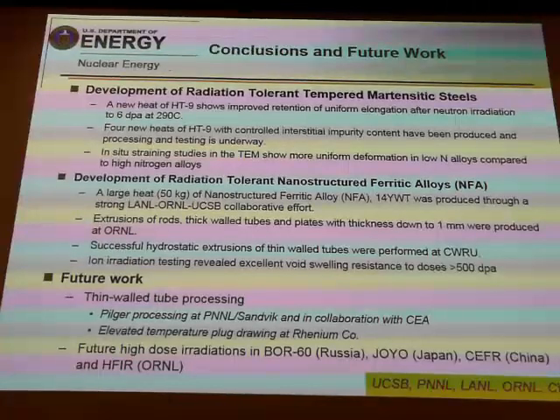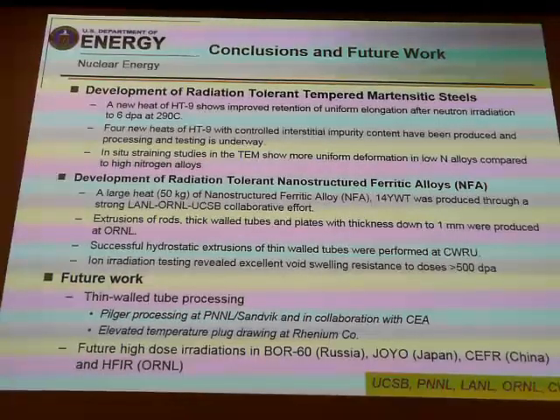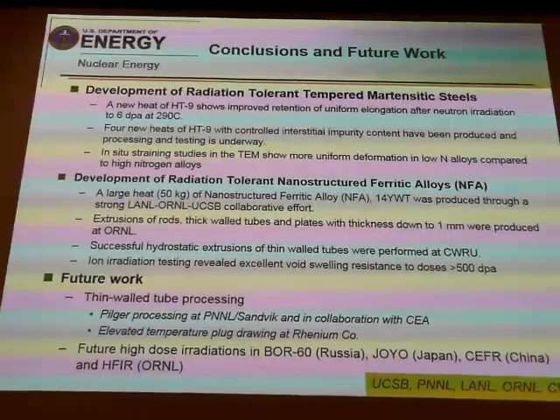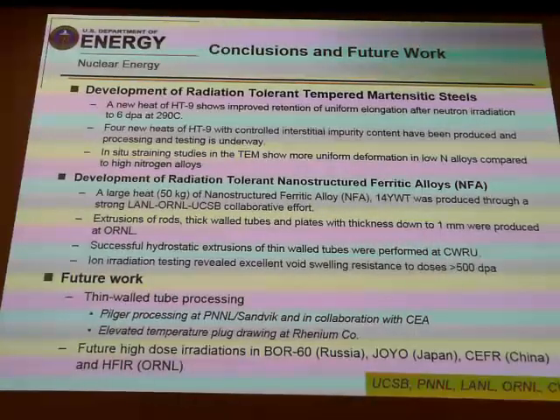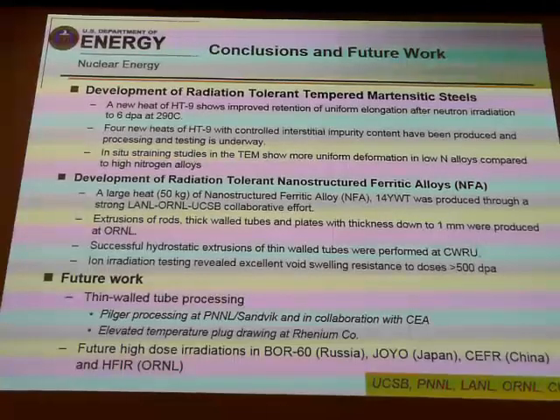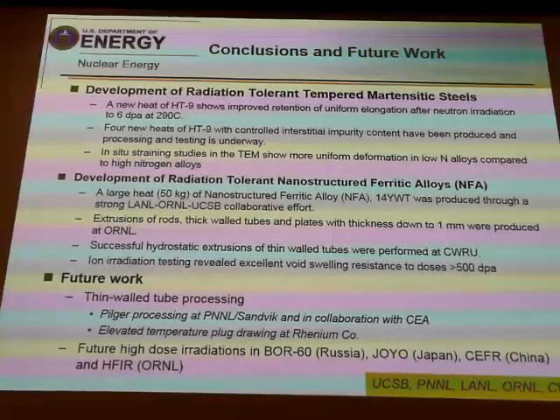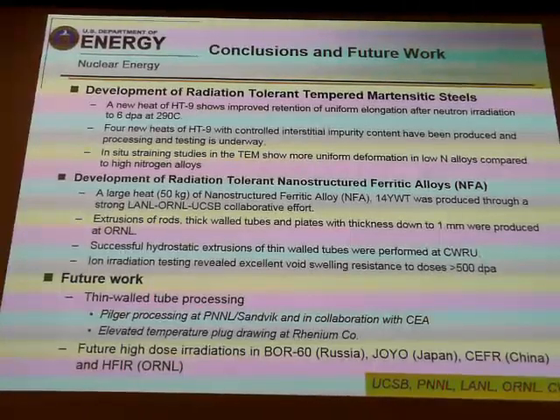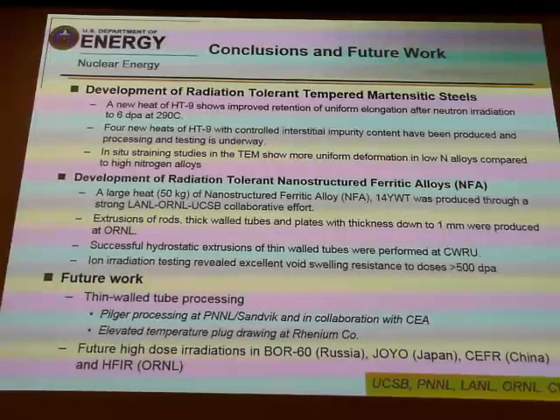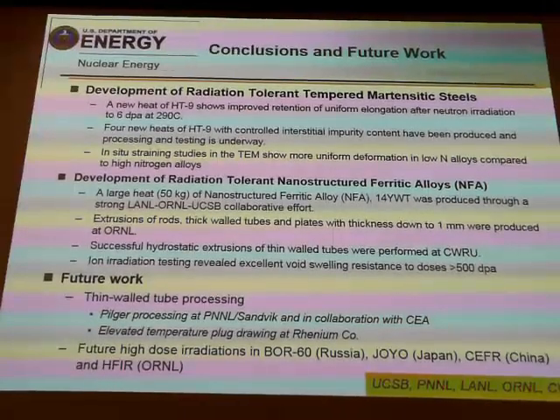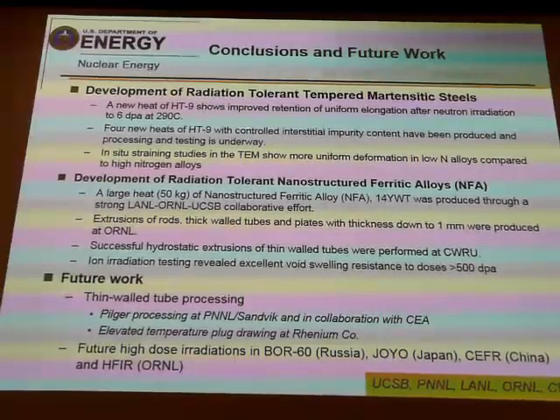Exactly. But at low temperatures, where you run into that issue, and I think it's below 300 degrees C, you put the oxide particles into solution, but they don't precipitate. So that's where you could run into an issue where you actually lose them. On the low temperature side, you get in trouble. Yeah, but it's not really an issue for fast reactor application. You're not running the reactor at that temperature. For fusion, it might be an issue because they do have cold areas in some places where they get dose at low temperature.